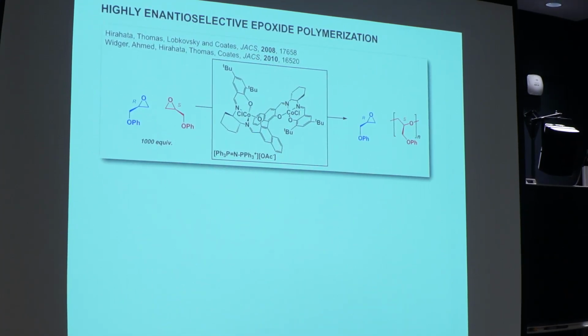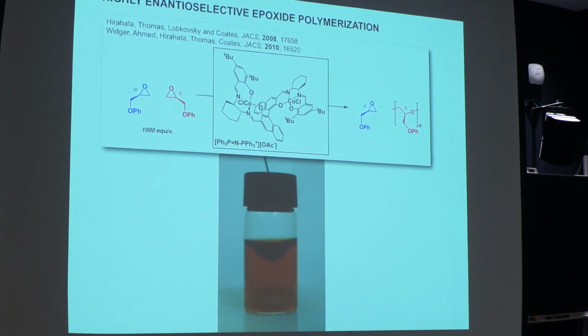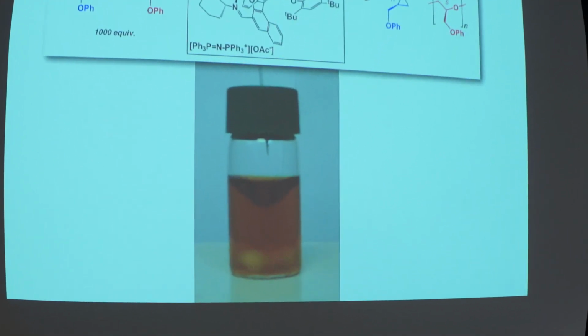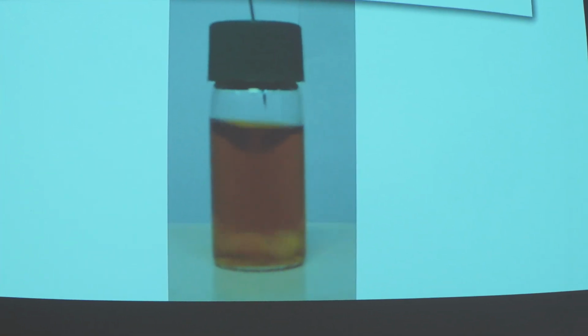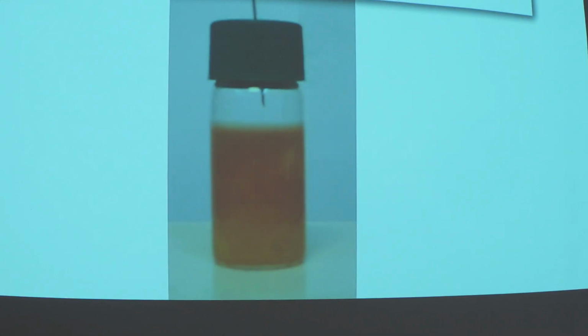So I wanted to show a video of this, and we had to use a bulkier epoxide because if you do these with propylene oxide, sometimes the vials blow up because they get really hot and the gas expands. So this is a catalyst in solution, and we're injecting this much bulkier phenylglycidyl ether, and so you can see it inject. And so right now, again, the yellow is from the cobalt complex. We've added 1,000 equivalents of the epoxide. And this is a nice projector. You can start to see maybe that it's a little cloudy, and now you can really start to see that something's forming in there. This vial, by the way, is pretty hot because we just ate up about 500 equivalents of epoxide in about 30 seconds.